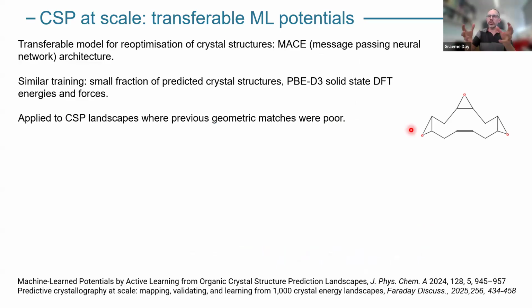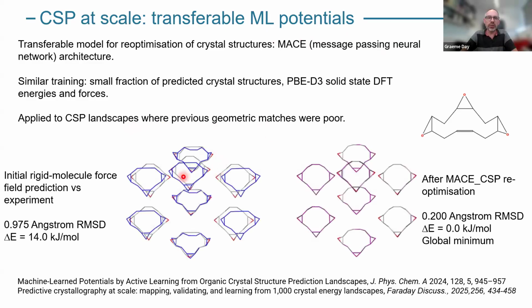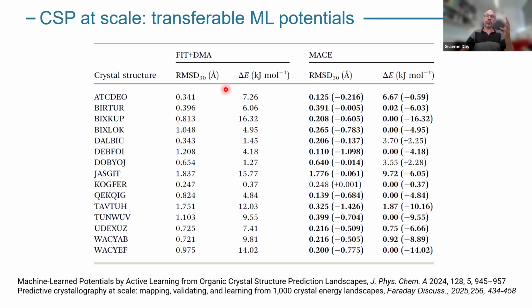We wanted a model now which can correct the structure in case these molecules get distorted by being in the crystal structure. And so we trained a different machine learned potential. Now it's a message passing neural network in a similar way. But what we see is that now it improves geometry. So on the left was our original prediction. On the right is an overlay of experiment and prediction after training an even better machine learned model. Okay. So we're getting those RMSDs in terms of geometry much lower, and in terms of energy, a lot better as well. Okay. And overall, all of those originally very poorly ranked structures really come down after we apply this machine learned model.